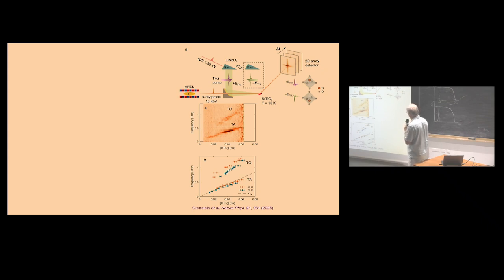is showing that they pumped strontium titanate using a terahertz beam generated from lithium niobate, a nonlinear optical crystal, and they investigated it with time-resolved X-ray scattering. They see the diffuse scattering, and from this time-resolved and space-resolved data, they can calculate the frequency of the excitations, which are seen here, and they observe that the transverse optical phonon should go to 0 or to some low frequency here, but it's not completely seen at the gamma point. It is the Brillouin zone wave vector. 0 is here, and here is the acoustic branch.